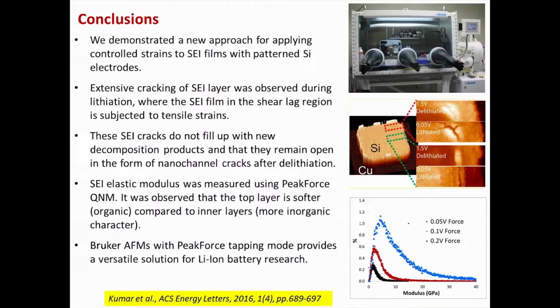So I will come to the conclusion slide with this. We have demonstrated a new approach for applying controlled strains to the SEI films with patterned silicon electrodes. Extensive cracking of the SEI layer was observed during lithiation, where the SEI film is subjected to tensile strains. An important observation was that these SEI cracks don't fill up with new decomposition products, and they remain open.